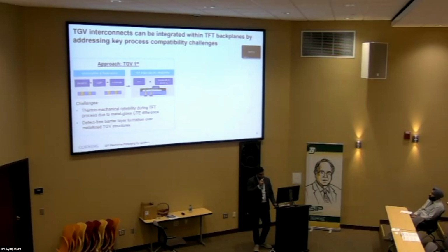So basically you have a glass panel with TGVs already, and then you metallize the TGVs, planarize them, and then fabricate the TFTs. You might see the issues already here, right? Because metallizing the TGVs, they have to be fully filled. That comes with a problem like thermomechanical reliability, because glass CTE you can tune from display glass to maybe around 3 ppm per degree C, whereas copper is around 16.